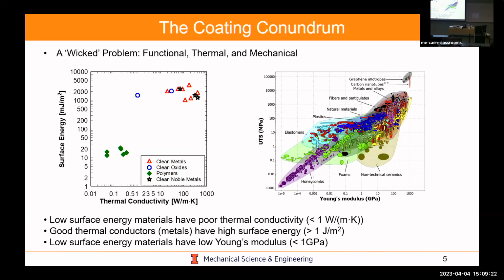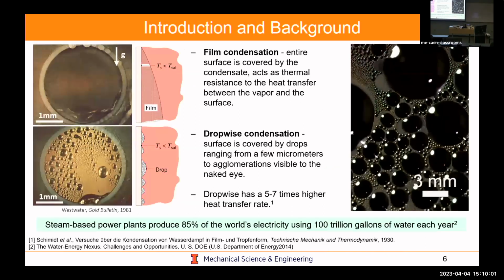You can see here the ultimate tensile strength as a function of Young's modulus. Polymers are down here, but ceramics and metals have great properties, but they have very poor functional properties. So because of this, for thermal-based applications, you want low surface energy materials, but they have poor thermal conductivity, typically less than 1. Good thermal conductors like metals have high surface energy, which is not what you want. And low surface energy materials have low Young's modulus. Again, we just talked about polymers. And so you're at this interface where you're trying to develop materials which have good durability, can last, and give you the enhancement that you want over many years, ideally, but have mechanical properties which really don't work for you, okay?